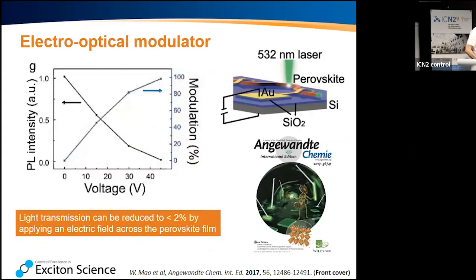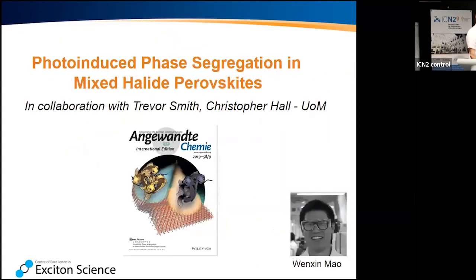Okay, and then what we're doing is we sit at the end of that wire, and we look at how much light is coming out at the end of the wire. And we look at that as a function of the electric field that we apply across the perovskite. And there we can see that we can almost completely shut off any fluorescence simply by applying a field. So what we have built here is an electro-optical modulator with a perovskite material. Cool. So there's one application.